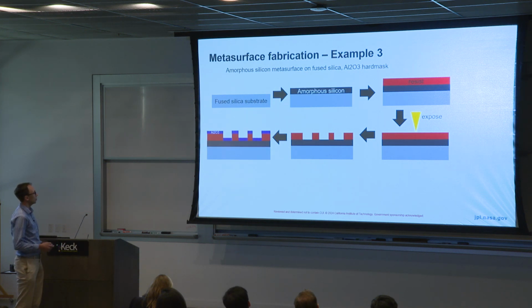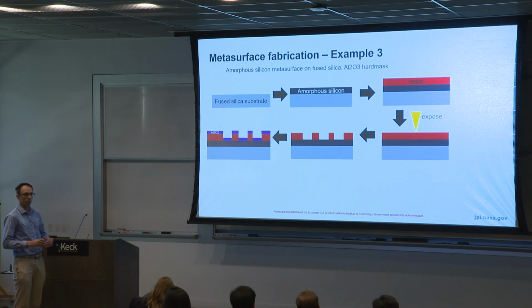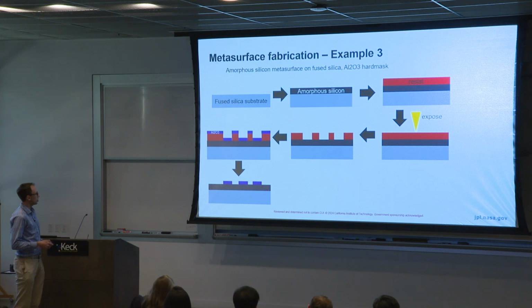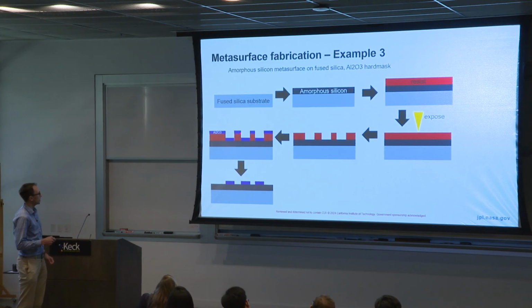So we're going to evaporate aluminum oxide, or I should say, we want to deposit aluminum oxide. And now it starts to matter what method I'm using to deposit this material. So now I'm deliberately choosing a method that's not conformal. So I have these sidewalls of my photoresist are now open, they're exposed. So that means that I can, if I put this into a solvent, I can dissolve the photoresist, and then